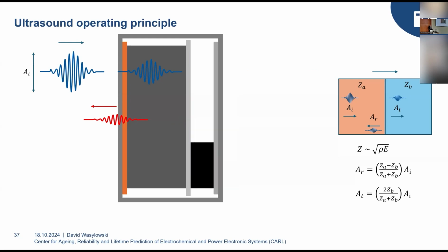And the same thing works for a mechanical defect. For example, let's assume we have parts of the cathode missing, and this hole is just filled up with electrolyte. Then again, we have a pretty large material interface, acoustic mismatch within the battery, and we get this fairly large reflection within the battery, further decreasing the transmitted amplitude.